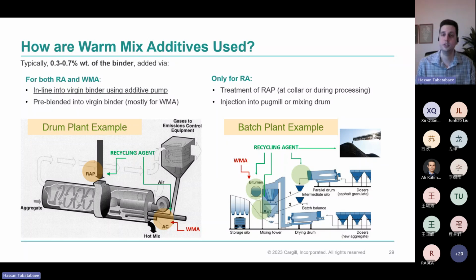This is usually used with an additive pump and it is injected into the virgin bitumen. At a drum plant, that would be into the pipeline going into the drum for a continuous plant. And in a batch plant, that would be going into the balance of the bitumen with an additive pump. As the bitumen is filling into the balance, the additive is added in there.